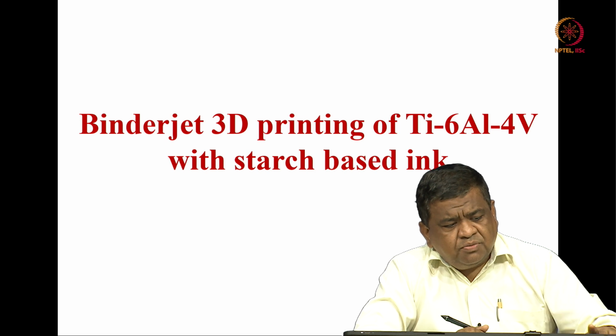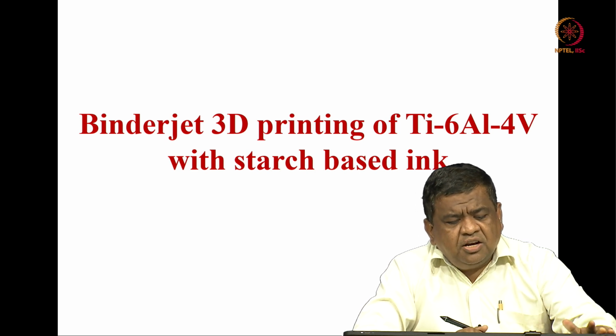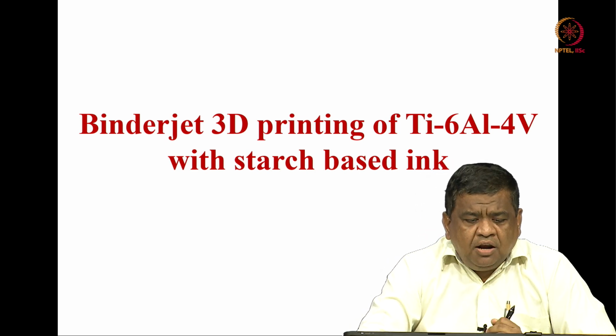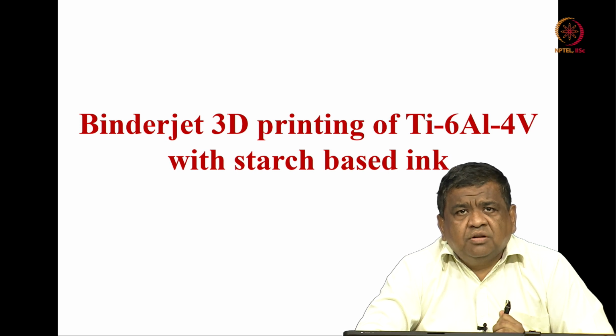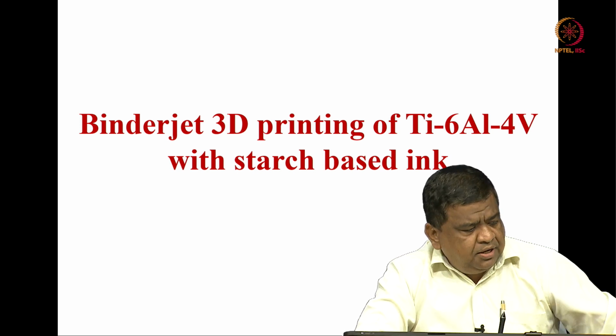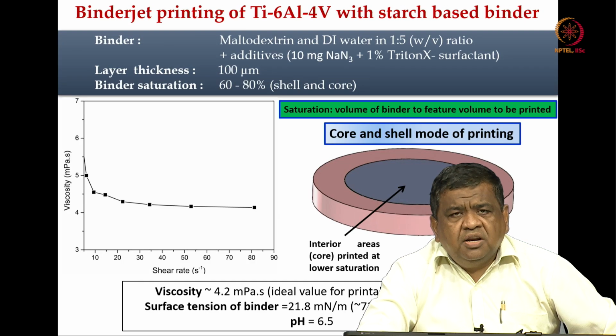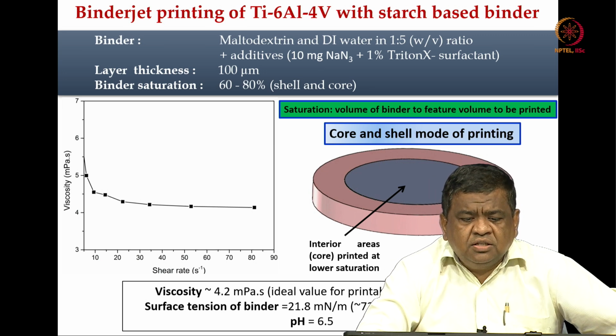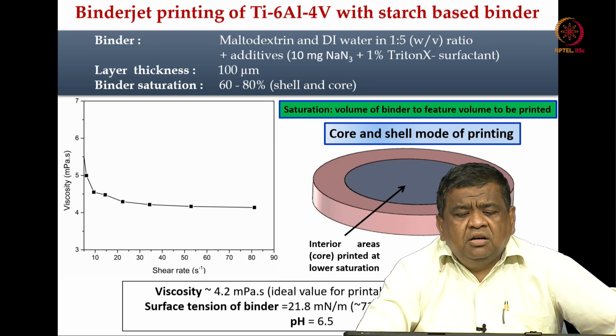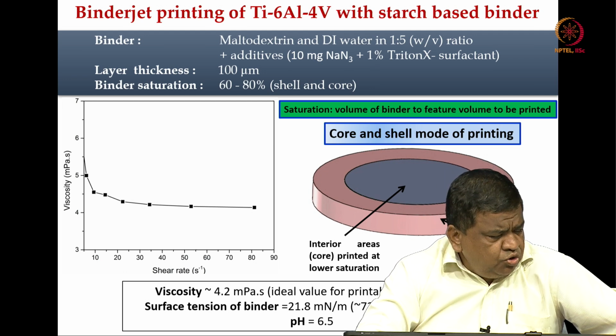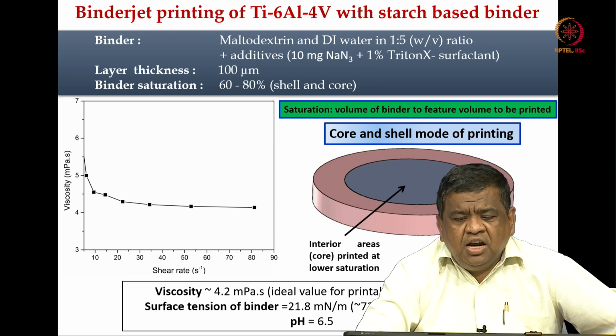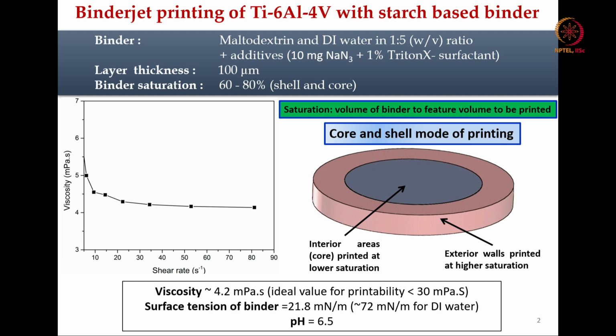We have started working on binder jet 3D printing. The first material that we have tried is Ti6Al4V, and we have used several binders. The first binder is a starch based ink. So, what are the experimental details? We have used maltodextrin and deionized water in 1:5 ratio, and we have used certain additives like sodium azide and 1% Triton X surfactant. Layer thickness we kept at 100 micron and binder saturation was 60 to 80%, the shell to core.